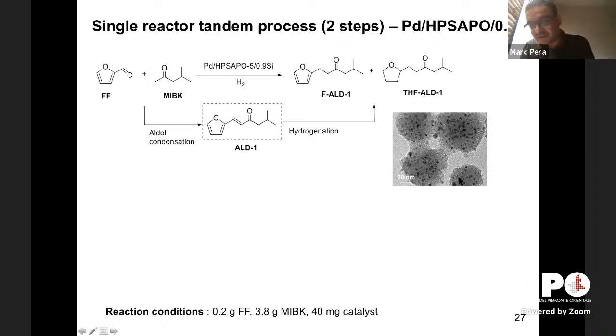So this is a picture of our very nice particles with a very well dispersed palladium. Now this palladium is outside the particle. This contrasts with what Urbano was showing before. In his case, he could confine the palladium in the mesopores. So it's different, and that affects also the selectivity. In our case, we only hydrogenate this double bond here, and also the furanic ring, but we don't touch the carbonyl group. In his case, he can touch the carbonyl group. This is something very interesting.